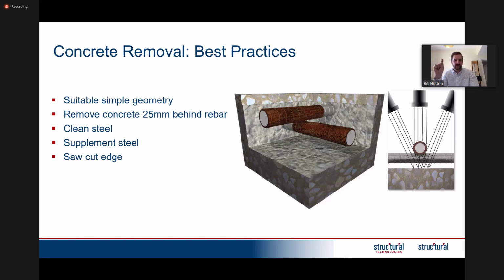You can measure the cross-section loss. Typically, the rule of thumb is if you have cross-section loss of between 10 to 20%, then you should engage a design professional. So you should engage an engineer, and they will determine how much supplementary steel needs to be added.